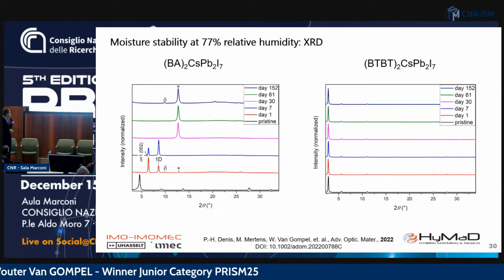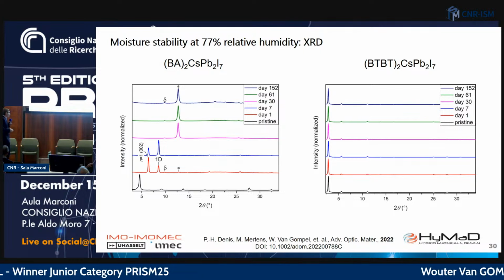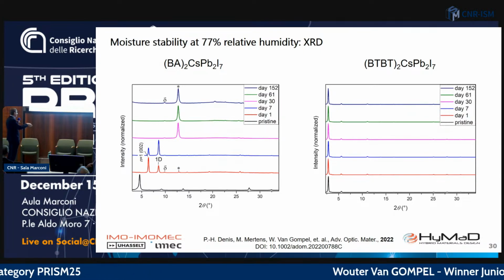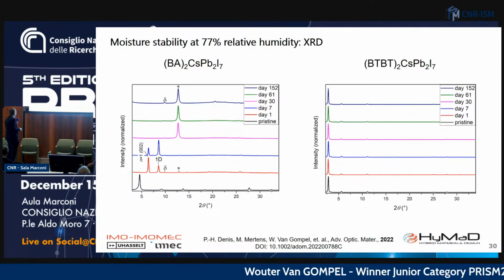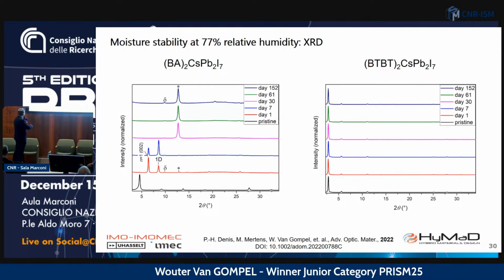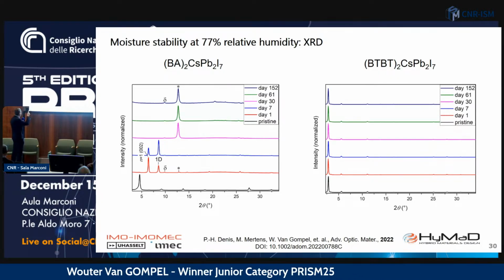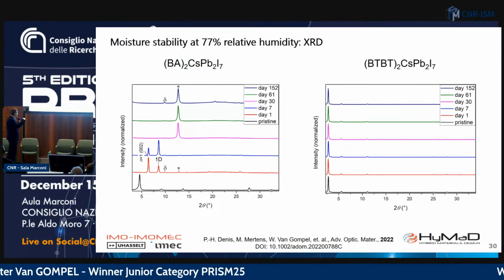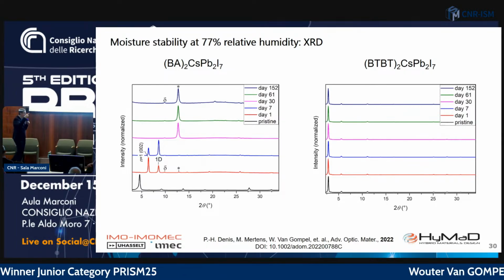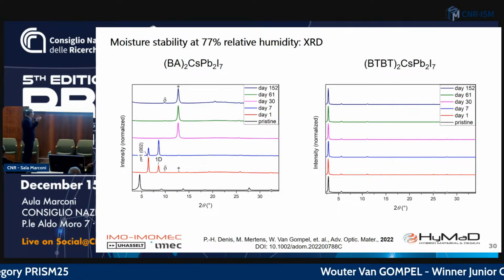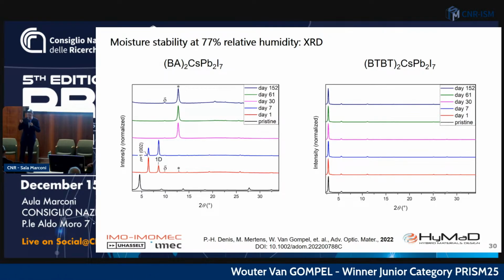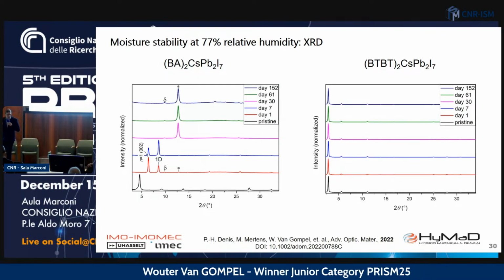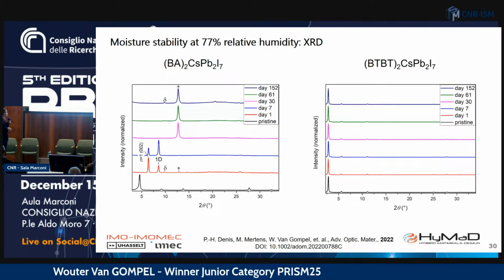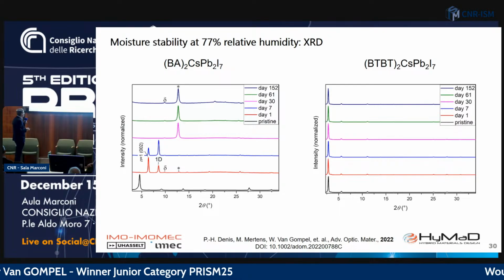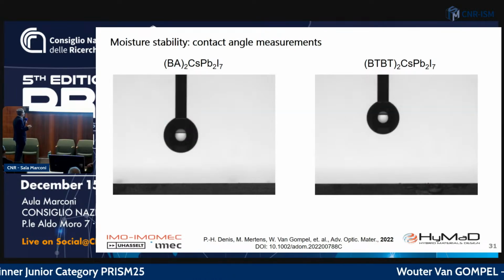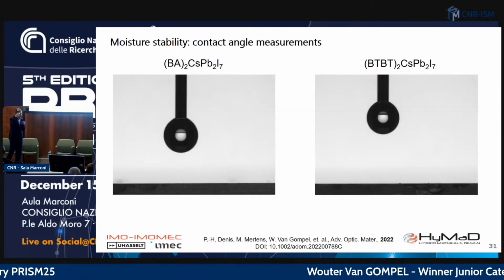You can also do it via X-ray diffraction, of course, because absorption spectroscopy can hide maybe some things. But also in XRD, you see the same, that the reference degrades immediately via a very complex pattern of different phases. The one we designed is unchanged over this course of 152 days. So again, also in XRD, you see that these materials are very stable under moisture, which is not very typical for these halide perovskites. And so we wanted to investigate why that's the case.